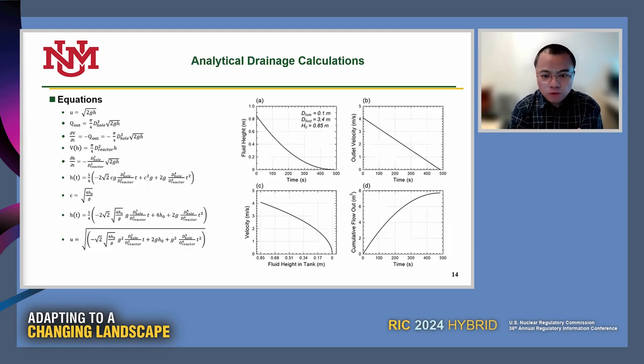To get the initial flow rate boundary, we use an analytical solution calculation to get the velocity from the drain hole. Figure A shows the fluid height in the reactor, so the molten salt level in the reactor over time when there's a drain. Figure B shows the outlet velocity versus time. As you can see, the initial velocity is 4 meters per second, and then some other velocities, and then the flow rates, as you also can see in the bottom two figures. The left-hand side shows all the equations for the calculation. There's one assumption, that each time step should be larger than the momentum time scale that we are using in the CFD, and for each time step we assume steady operation so that we can get the solutions here. It's the ODE, equation number six, so we can do the calculation from it.